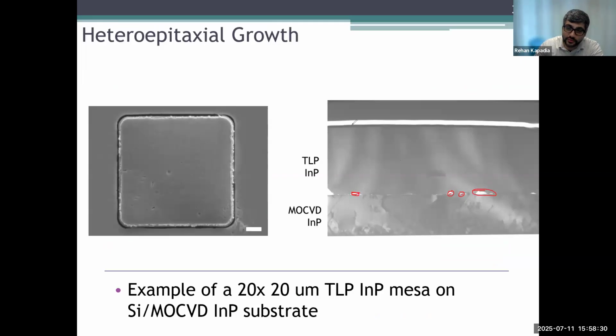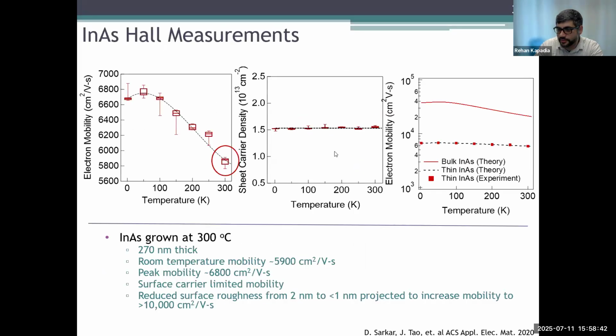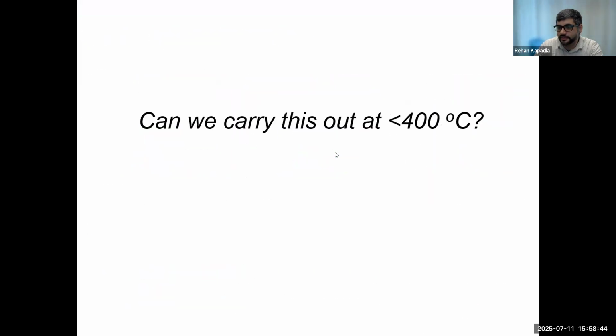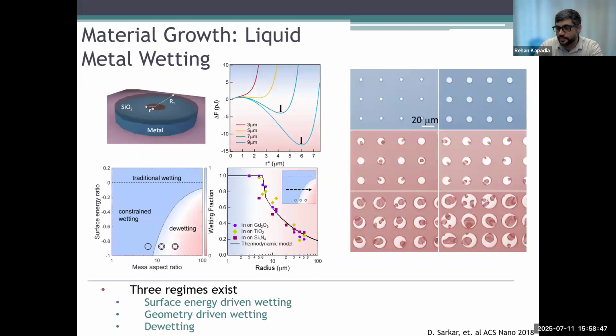The origin of those voids is most likely, let me clear all these rings, we believe it's coming from the physics of what happens here. I didn't talk about this before, but fundamentally, the mechanism of de-wetting of a liquid film is a nucleation and growth problem. It's just that what you're nucleating and growing is a void.